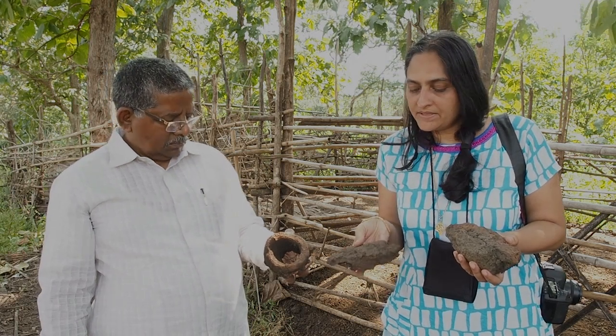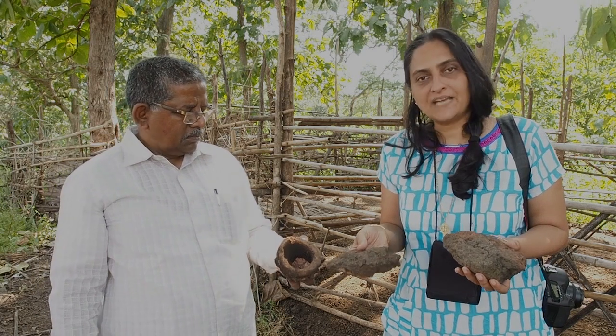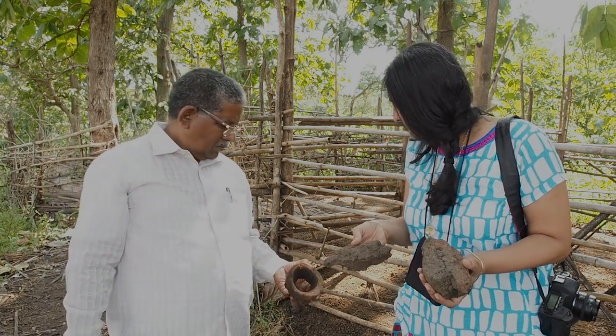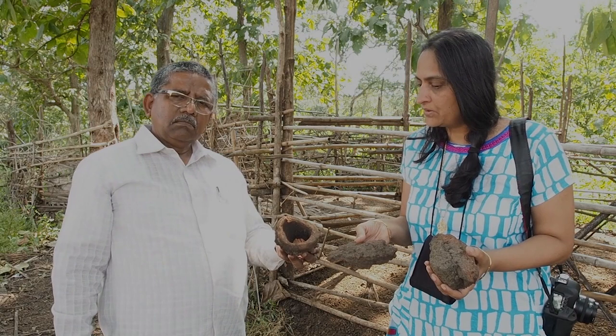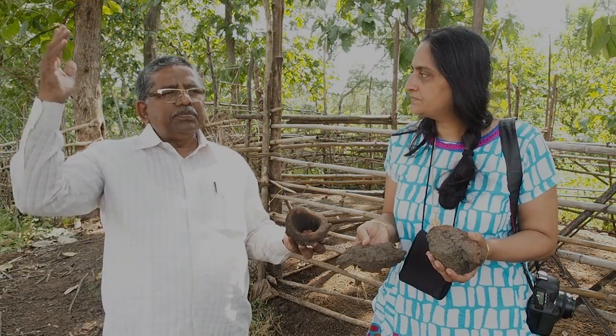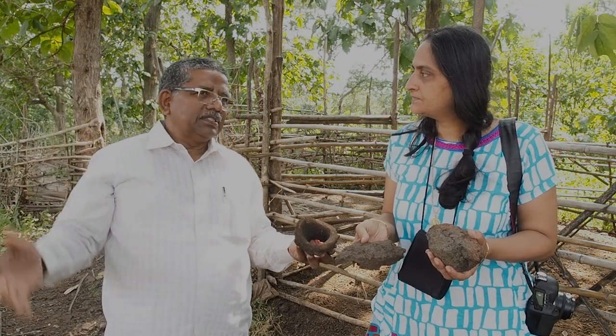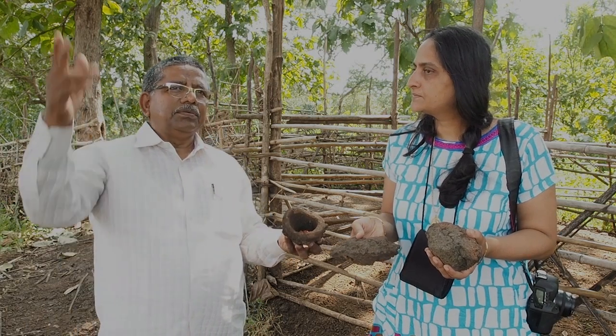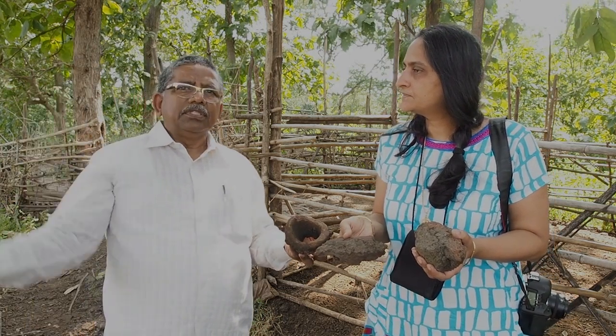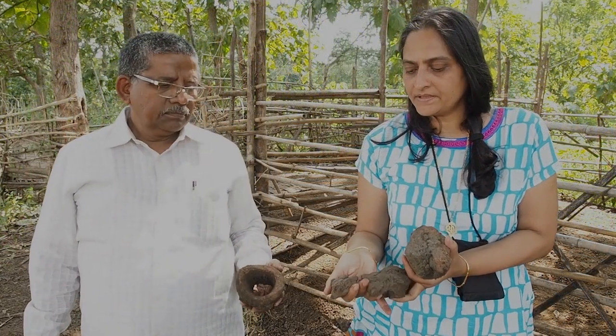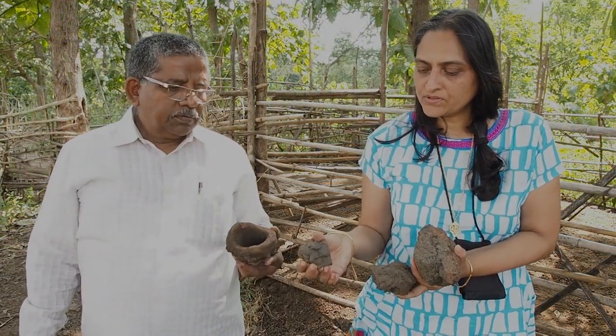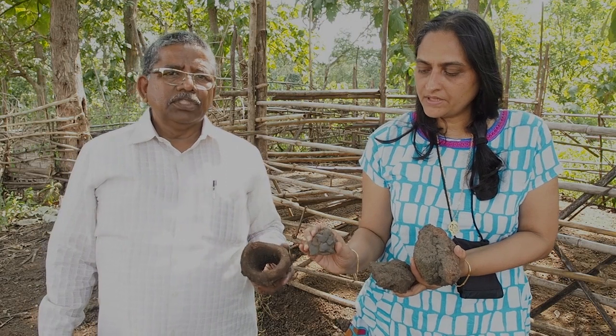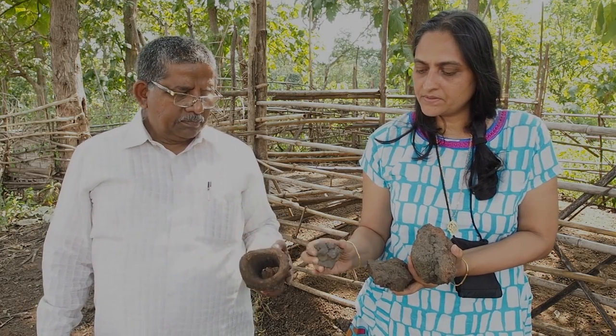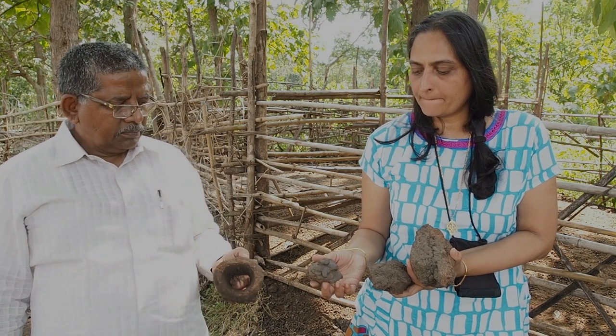So these pieces which you're seeing are broken pieces of tap slag, and all of this indicates that there was extensive iron smelting activity going on here. A series of heaps, miles together, spread in the forest, particularly in Kalleda, Lakshmipuram, Dasturabad, Bundagunam, Chittala. There are several villages in Adilabad. And this piece in fact shows the typical flow structure of tap slag. It's a very good quality tap slag with the viscous, flow texture.